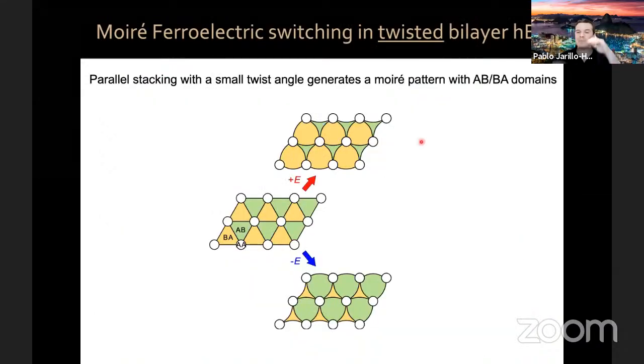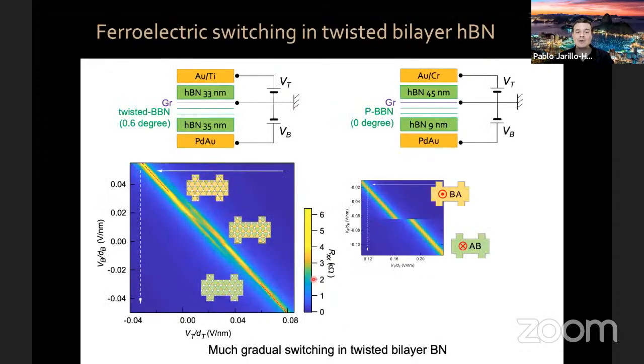Now, if you make devices with a small but non-zero angle, then you will naturally form this honeycomb structure with AB and BA domains, similar to graphene on top of graphene, but now these are hexagonal boron nitride domains, AB and BA. If we apply an electric field, it will be favorable for one domain configuration to grow, let's say the BA. If we apply the opposite electric field, the other configuration will dominate, let's say the AB. So indeed, if we fabricate these devices, these are data for a twisted bilayer boron nitride with a 0.6 degree twist angle. You can see that the ferroelectricity now shows these two peaks coexisting over a broad electric field range. This corresponds to the situation as we're going from one domain slowly growing the other domain type. This is very different from the abrupt behavior we have for 0 degree devices.